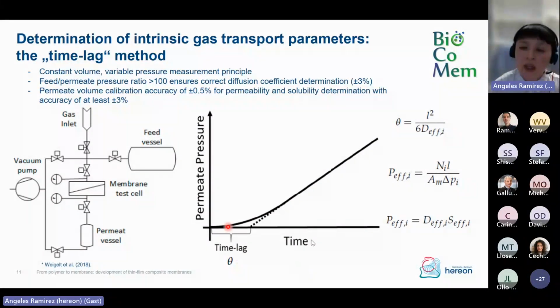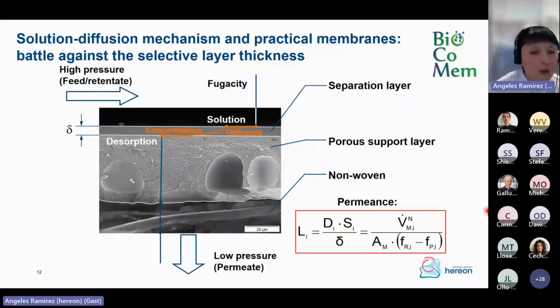Now, from this plot, as we have an example here, we can determine, first of all, from this slope, when the measurement is at its steady state, the permeability coefficient. And from the time lag, that is the time that it takes the measurement to reach this steady state, that is the transient state, we can calculate the diffusivity coefficient. And now with these two parameters, we can already calculate the solubility of a gas in the polymer. So from one measurement, we can obtain the three most important parameters for gas transport in a polymer. So now, if we are satisfied with it, we continue to prepare membranes. And for this, the most important feature that we need to consider is the thickness of the selective layer.